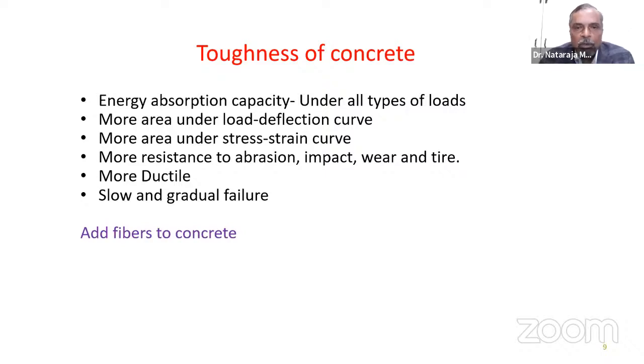And we have the concept of fiber reinforced concrete, and steel fiber reinforced concrete in particular. So the energy absorption capacity means more area under the load deflection curve. I really don't know whether you are all aware of the fact that the area under the load deflection curve, especially in flexure, keeps on increasing as the amount of fiber is increased. And of course, there is aspect ratio and volume fraction coming into the picture as these parameters are increased. So definitely the area under the load deflection curve also keeps on increasing. More area under the stress strain curve. The moment I say stress strain curve, obviously it is the stress strain characteristics of the concrete in axial compression. So that is where the improvement in the toughness, improvement in the energy absorption capability of the concrete.